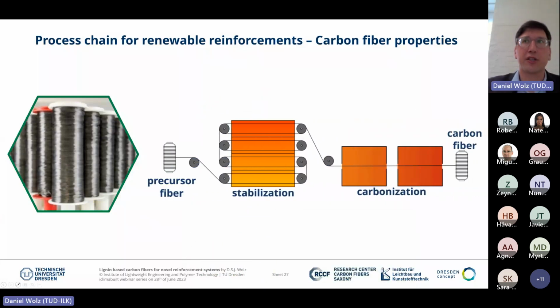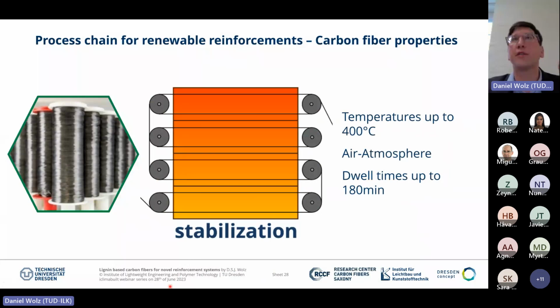So, but how can we challenge it? Looking at the typical carbon fiber technology, we start with the precursor fiber, we go to stabilization, carbonization, and have at the end the carbon fiber. Stabilization usually works at temperatures up to 400 degrees Celsius in an air heated convection oven, and times between 40 to 180 minutes, depending on the manufacturer. The now standard of stabilization is in the range of 40 to 80 minutes, meaning less time to stabilize.